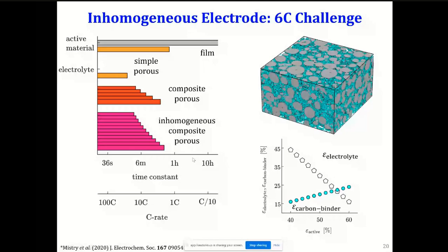And the next generation challenge is talking about extreme fast charging, which means you want to charge this at 6C, which would be less than or equal to 10 minutes. And then what would happen is some of these locations would have a more sluggish transport than you can handle. So even though macroscopically, if you just look at the electrode average porosity, it would look like, oh, you're not running into limitations, this inhomogeneity would indirectly bring you back into transport limitations when you work with inhomogeneous electrodes.